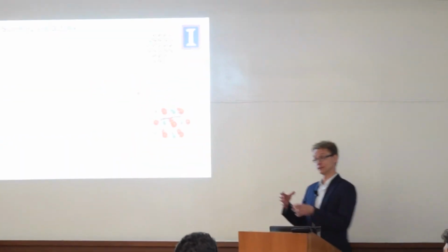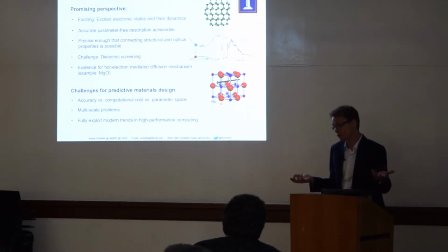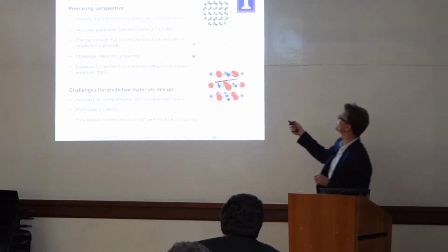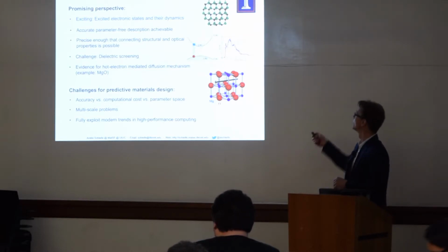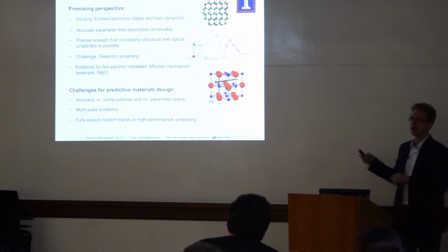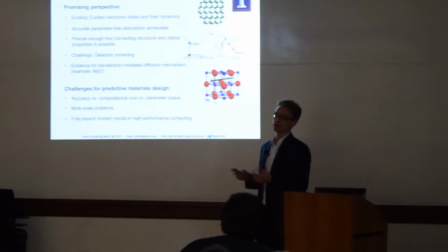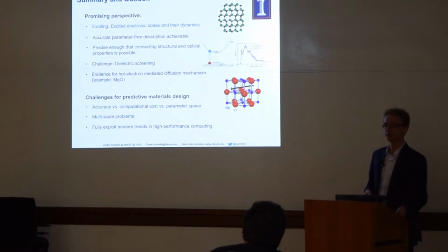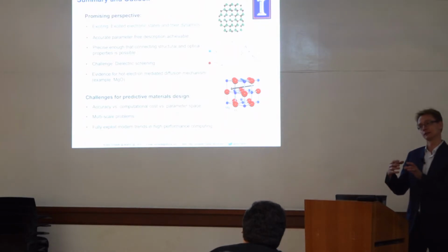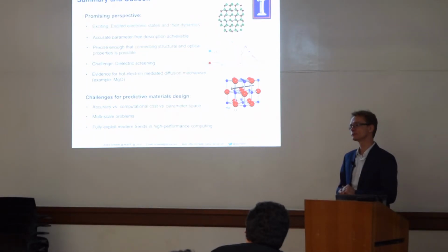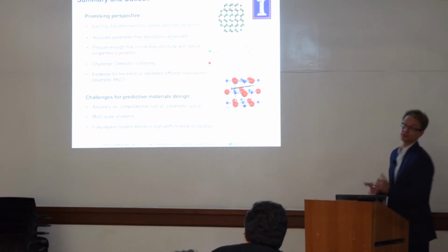Right, so that can certainly happen if you look at a specific surface and you would compare, let's say, different surface orientations to a bulk spectrum, that would differ. But the spectra I showed for those nanocrystals, in some sense you can see those as an average over all the surfaces because we calculate the explicit nanocrystal. This is the actual simulation cell basically. And so you would probably average over those, and my guess is that in that case it doesn't matter as much anymore because that stuff averages away and you get again this idea that the first nearest neighbors are similar in both bulk structures, and then you have to go to larger lengths to see a difference. But it is true that at higher energies there is a difference between the two.